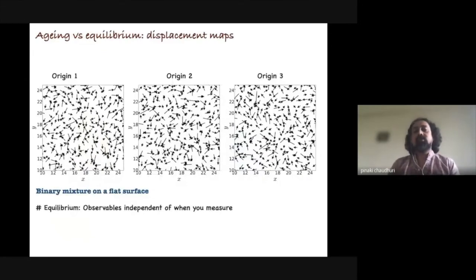So we try to illustrate this through computer experiments. What I show here is that the idea of equilibrium is essentially that any observable you have is independent of when you measure. So if I measure something at time origin 1 or time origin 2 or time origin 3, it really does not matter which time origin I choose. What we plot here are displacements of particles between time origin and time origin plus delta t. And you see that, independent of the time origin, statistically the maps all look the same. There is no difference, and that is what you expect in equilibrium.